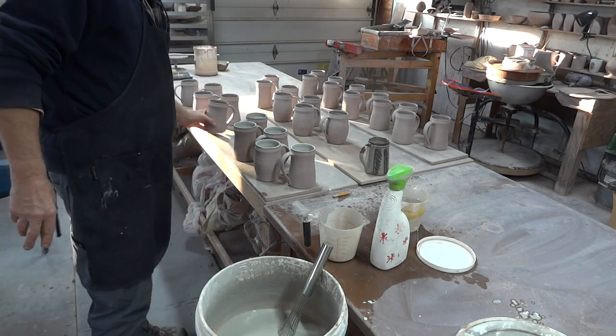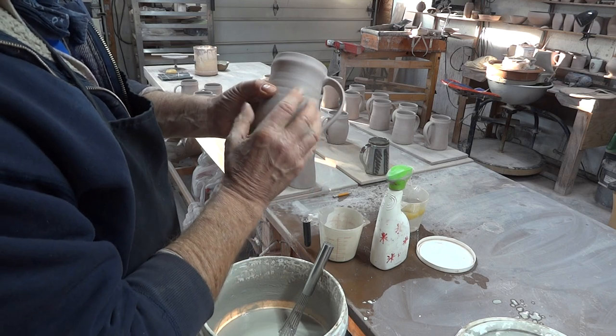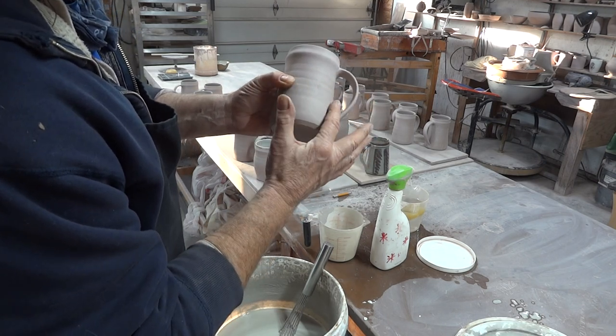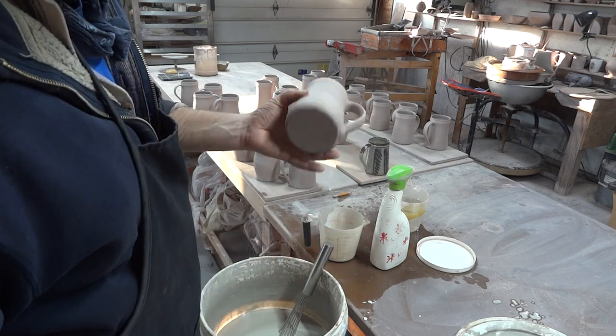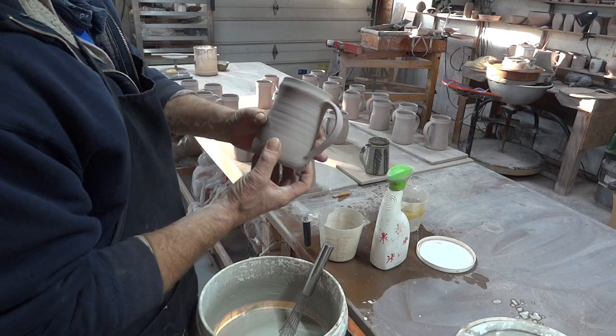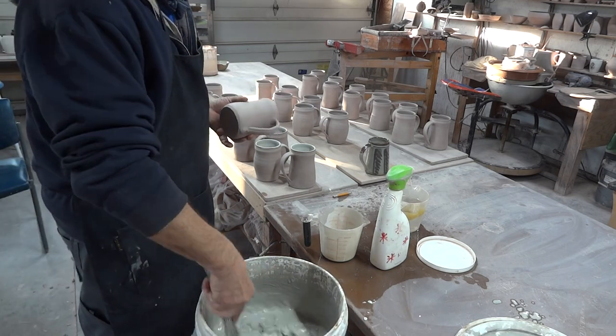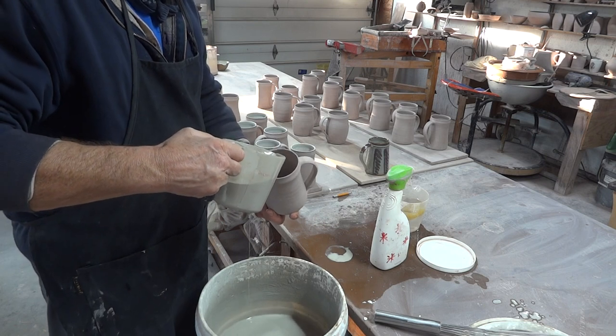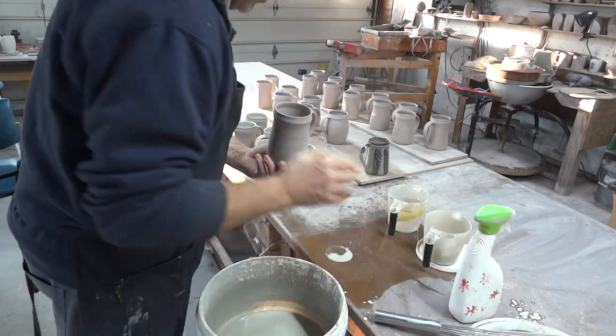The first time I did this I applied glaze to a pot that was not dry, and I observed the glaze on the outside of the pot remaining on the surface while the pot continued to shrink. I thought it was just going to fall down off onto the kiln shelf. So instead of glazing it leather hard, I glazed it bone dry — because it's already shrunk and hasn't got any more shrinking to do except in the firing. And it worked a treat. These pots come out as good as ones that have been bisque fired — you can't tell the difference. I completely eliminated the cost in time, labor, and gas of having to do that bisque firing.